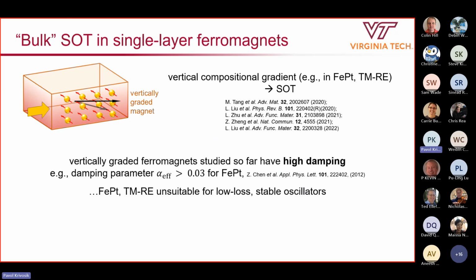However, these previously demonstrated materials are all very well known, or actually infamous, for having very, very high damping. Right? So for those of you who are familiar with Gilbert damping parameters, these materials typically have damping parameters on the order of, let's say, 0.01 or even greater. So that's about 10 times greater than many of those very well-known soft ferromagnets with damping parameters on the order of 0.001. So as it turns out, even though it is indeed possible to generate spin orbit torques in such materials, iron platinum and so forth, they are unfortunately very much unsuitable for low-loss device applications.